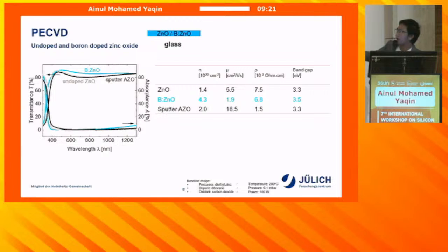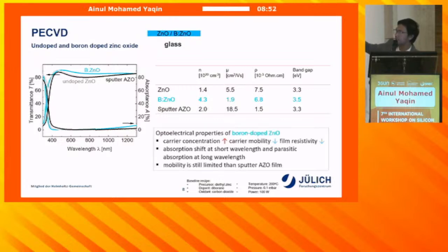If we look at the electrical properties comparing the undoped and boron-doped zinc oxide, with the boron doping you definitely have more carrier concentration. But when you introduce impurities, you have more carrier concentration, which can also act as scattering centers. Therefore, you have a reduced mobility. But overall, with the boron-doped zinc oxide, the resistivity drops, which is promising. And then if we compare the boron-doped zinc oxide to our well-developed sputtered AZO, there is still a gap in terms of the mobility, which requires further investigation and optimization.